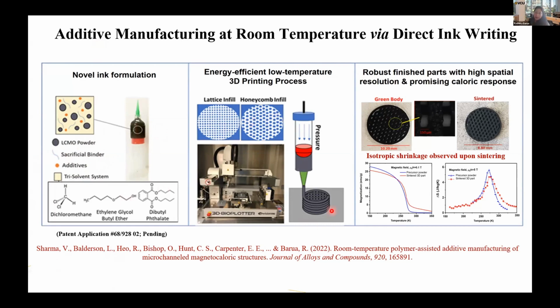We use that ink to get the structure that we want, and then once we've done that, we burn away the ink. We see some shrinkage happening in our samples, but what we end up with at the very end is a consolidated metal part.